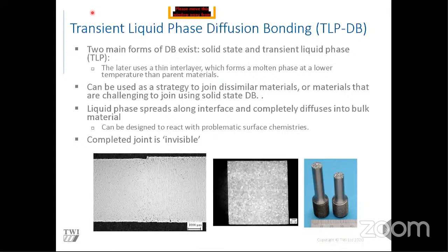TLPDB can be used as a strategy to join dissimilar materials, or materials which are difficult to join using solid state processes. The liquid phase that we try to create spreads along the interface, and it completely diffuses into the bulk material, so the actual resultant joint is invisible. Here's an example at the bottom - that's where the joint was. When we did the tensile testing, the joints actually failed in the parent material, so we got higher strength in the joint compared to the parent material.